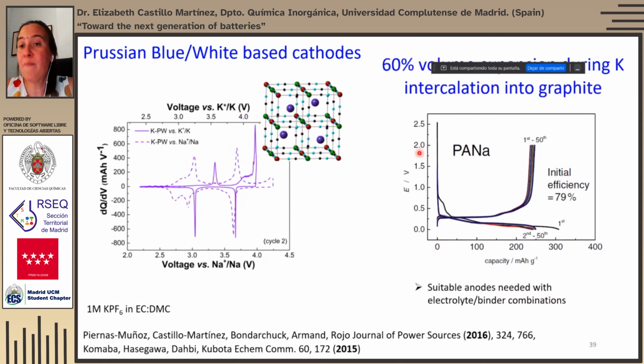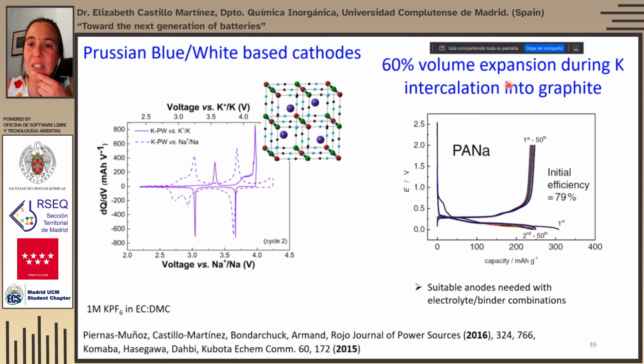For the anode, graphite does show a 60% volumetric expansion when potassium is intercalated into graphite. It's quite large, and therefore it is also interesting, and this is one of my current research areas, to look for alternative anode materials for potassium-ion batteries. Nonetheless, it can be seen that by changing the binder from typical PVDF to polyacrylonitrile, the first cycle Coulombic efficiency can be reasonable. I mean, 80% is a reasonable value for a first cycle, and the capacity can